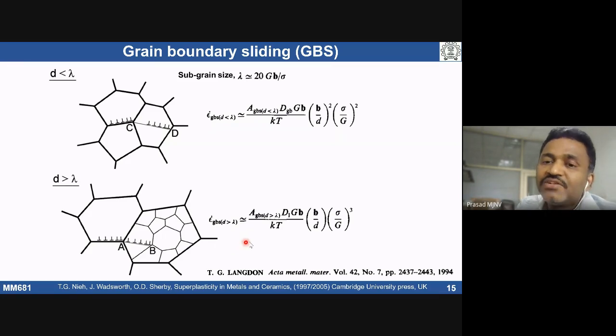In the other case, we are going to see some diffusion creep. Typically, coarse grains will undergo diffusion creep, which is going to accommodate the grain boundary sliding discontinuities. Is it clear? Whatever I said, these are constitutive equations to describe grain boundary sliding activity.